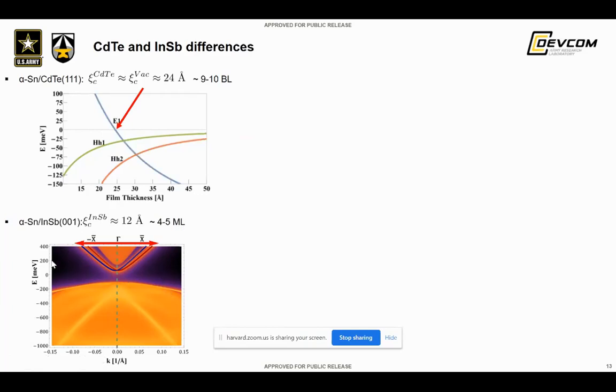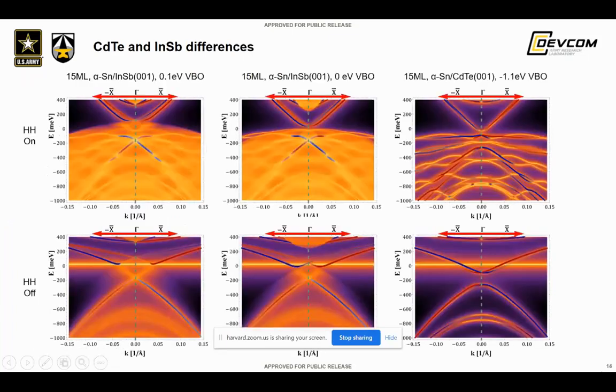Here are shown some ARPES simulations of data which shows this point, that you actually can see from this material that you still get minimal band gap and hybridization for a very thin layer of InSb. And these slides just show further ARPES simulation data using a comparison of CdTe substrates and InSb substrates and the differences that one can see from the expected ARPES data.